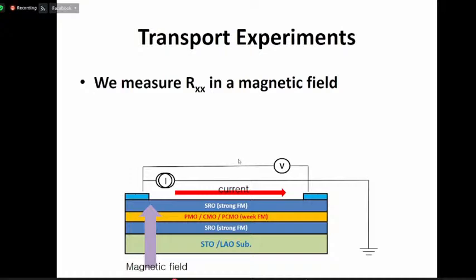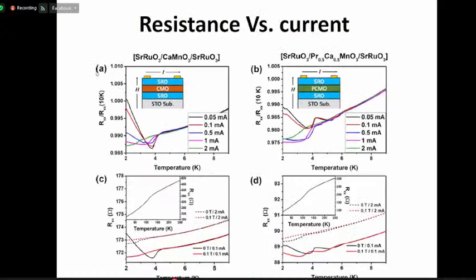And then we see some interesting things using the measurement of resistivity in a magnetic field. In this case, at very low temperature, below 4 Kelvin like this, the resistivity is going up, like the Kondo effect. But if we apply the magnetic field, this behavior goes down, like the red one. Also, depending on the current, the behavior changes very differently.